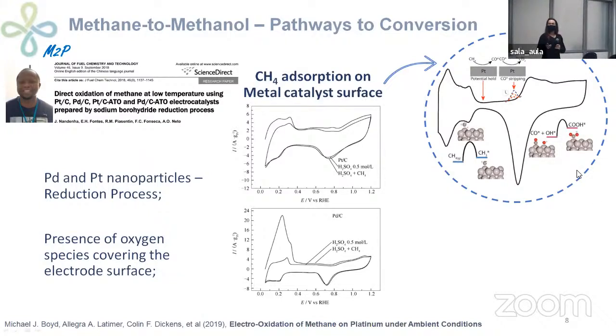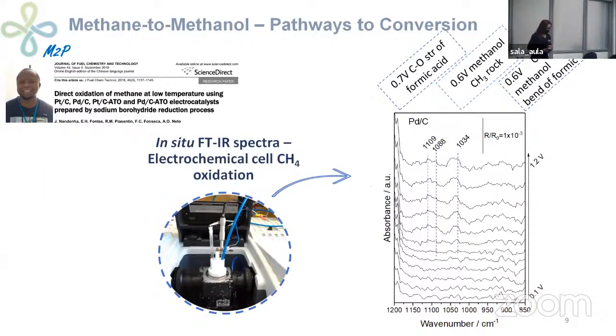Later, Boyd described the effect of methane adsorbed on metal catalyst surfaces, and described the formation of these oxygen species and, in addition, alkane radicals. Besides these results, we can observe the formation of other organic molecules, like formic acid, besides methanol, by in situ experiments with infrared spectra in electrochemical cells.